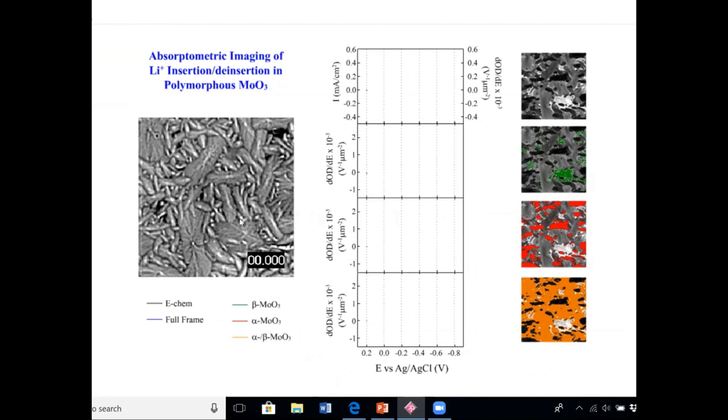Then what we're going to plot is as we apply a potential to insert lithium ions into molybdenum oxide, we reduce molybdenum 6 to molybdenum 5, and by charge compensation, this leads to the insertion of lithium into molybdenum oxide. We can record the overall cyclic voltammogram, but we can also use optical techniques to provide regions of interest where we know the chemical or structural identity of one of the polymorphs that make up this polycrystalline electrode. So it's color-coded in a beta phase,